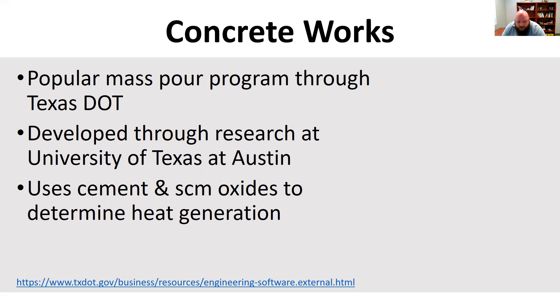There are other programs out there too. Concrete Works is a free program. You can plug in your cement and SCM oxide composition — the amount of calcium, silica, aluminate, et cetera — and it will actually generate heat curves. It's a model, so it's not perfect, but it's quite useful.